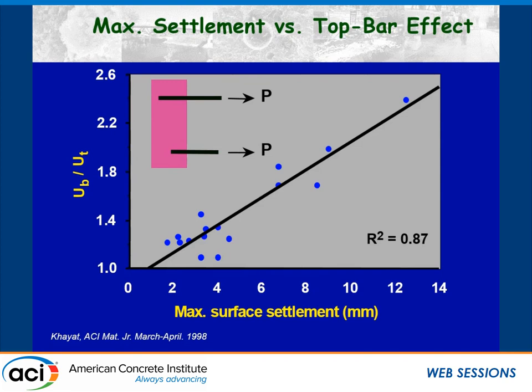And these are many studies, including flowable concretes and all the way from 6-7 inches into SCC. There's a clear relationship between the top bar effect and the maximum settlement. As the settlement increases, you have to provide more embedment of your rebars, more overlap of your rebars to develop the same pull-out load.